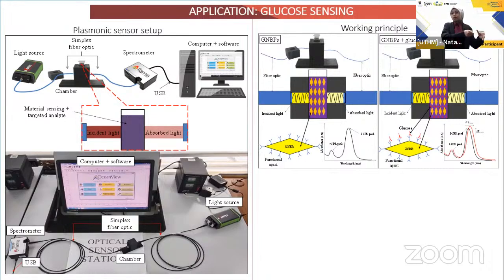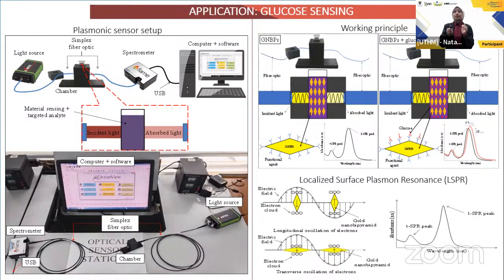Then light from the light source will be exposed to the chamber through the fiber optic. So when gold nanopyramids detect glucose, it can cause a spectrum shift in the localized surface plasmon resonance, or LSPR, spectrum. Then the spectrum will be recorded by the spectrometer, and the last step is visualization using computer software. For your information, localized surface plasmon resonance is the optical phenomenon conducted by all metal nanoparticles when they are irradiated with a specific wavelength, and it is very sensitive to surrounding medium change.